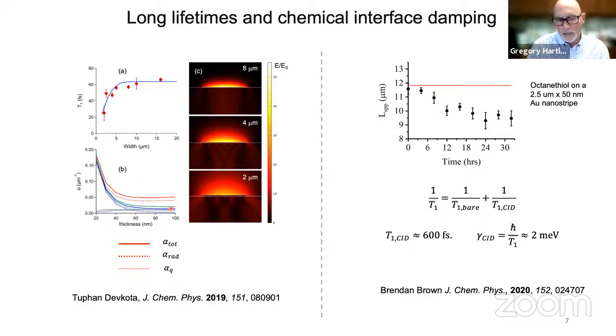The strange thing, or at least it was strange to me about this, is that when you look at that effect, you see that that increase in attenuation and reduction in lifetime comes about because of increased radiation damping, right? For the smaller structures, they're more lossy, they give off photons more easily. And what's strange about that is that for particles, radiation damping is larger when the structures are larger, not smaller. Here we see it's the opposite effect. Radiation damping is larger when the structures get thin or have small dimensions rather than large dimensions.